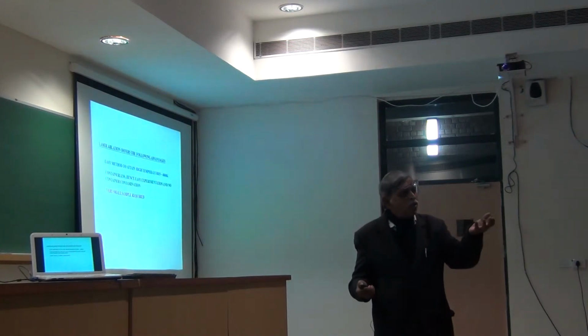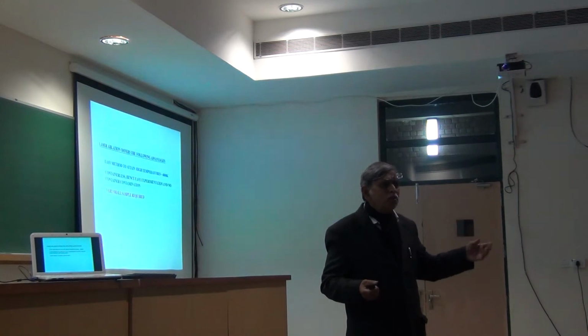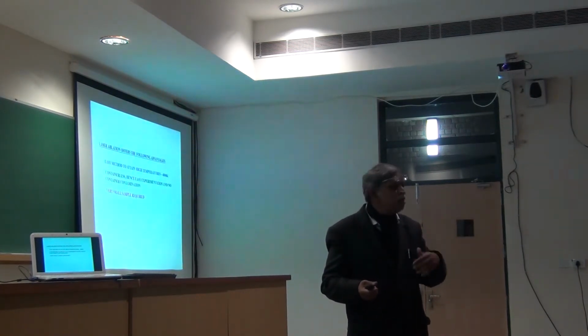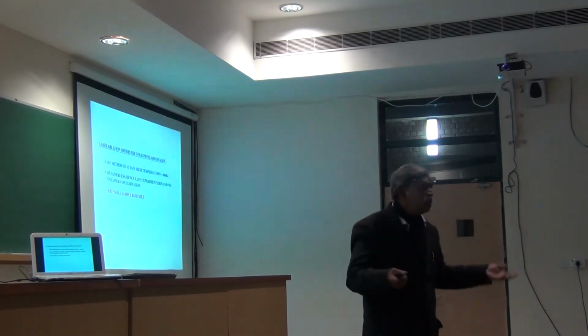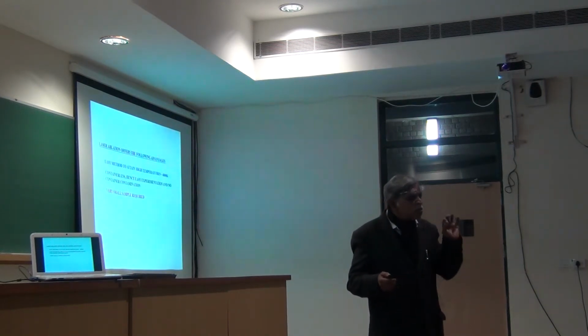You need a very small sample here. So all that you need is whatever the laser actually ablates and sends out, that's all. After doing the laser ablation experiment, you remove it, you only see some burnt spots here and there. And you can return the sample to whoever gave it to you, saying, look, I have used it. Basically, you have done the experiment. So there's very little sample that's required. If you have extremely small amounts of sample, you can actually get away with doing this experiment.